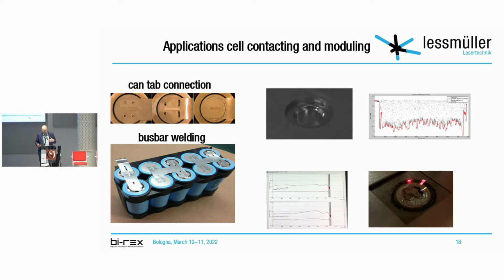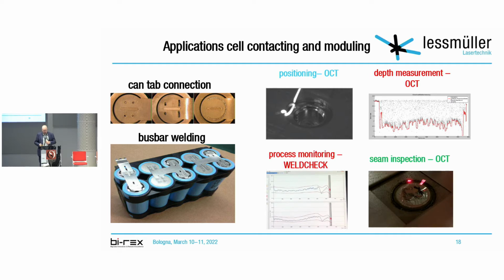So if the cell is finished, we have bus bar welding or can tab connection, and again we can use various tools. The OCT can identify holes very easily. You make 3 scans, so you have 3 points, and 3 points identify the center and the radius of a circle, and then you can reposition your welding path according to the hole that has been punched. Again, we can do depth measurement for connections and bus bar welding. We can do process monitoring with the WeldCheck, or we can do seam inspection after the welding, and we have a live demonstration for post-processing in the other room. So step by step, we can show you how this works in reality.